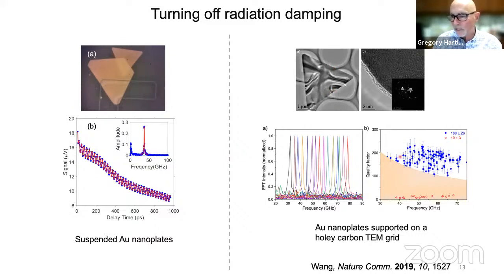On the support, you can get quality factors of about 100 to 200, average of about 180. So very, very large quality factors. The red lines here are for these same nanoplates out of the same sample on a glass substrate, quality factors on the order of 10. Again, typical of what you measure if you have something on a solid substrate, quite low, strong damping, loss of energy by sound waves going into the substrate, and small quality factors. Whereas if you have them on light substrates or suspended, you get much larger quality factors.